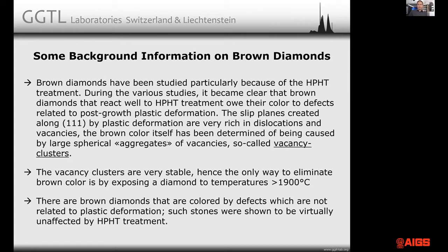Post-growth plastic deformations basically create slip along the octahedral crystal planes, and the slip planes created by such deformation are extremely rich in dislocations and vacancies. The color itself, there were many, many theories out there that said, well, it's just deformation. You take a diamond, you plastic deform it. It's the slip itself which creates the brown color. All of those have been basically found to be not accurate, and it was found that brown color is actually caused by vacancy defects.